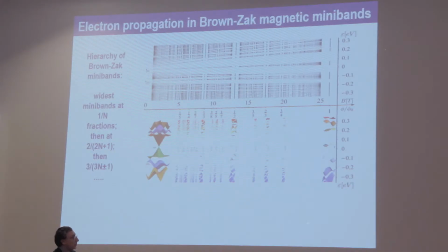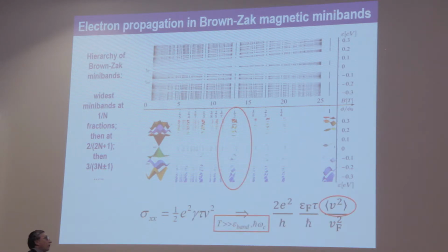The group velocity is a characteristic that you can approximately get by taking the width of the band and the size of the mini Brillouin zone. Here one has to be very careful just looking at the picture and trying to guess how it's going to look like, because the wider bands also have the larger support in terms of the size of the mini Brillouin zone. So one has to calculate these quantities really by taking enough points in the calculated dispersions, deriving the group velocity, and then analyzing this quantity. So the way how we look at it is that we think in terms of high temperatures.